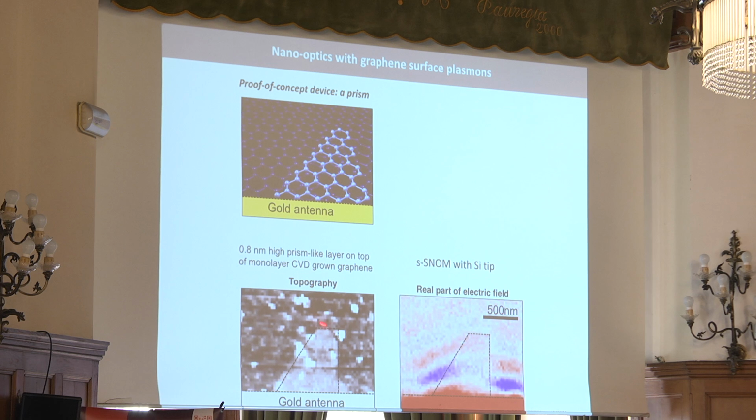And then by having this one, we put an antenna close to it, and we measured how it was launching the surface waves, and here you can see how they are not parallel to the edge, but at a certain angle. And if you evaluate these angles, you see that Snell's law is fulfilled for these waves. And it's probably the thinnest prism ever demonstrated, right? It's just 1 atom thick. OK, this was super nice, and it was only visible because we used SNOM and a silicon tip.